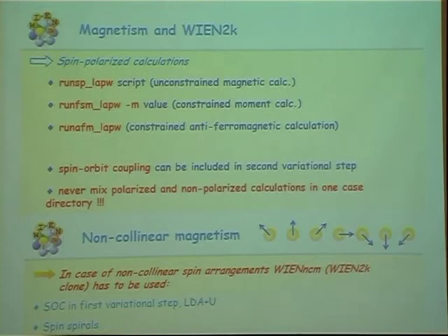If we start our SCF cycle with a magnetic moment sitting here, it probably will converge very slowly, but maybe it will converge to this energy and this non-magnetic solution. If we start here or here or here, then we will get this solution. So this is something which is not very favorable. It also takes many SCF cycles because usually such a situation is converging very, very slowly.